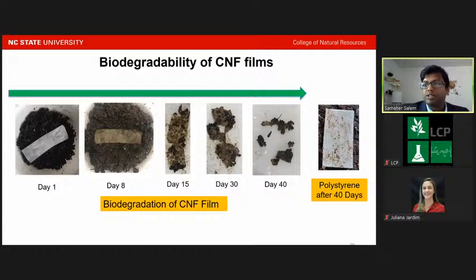And this makes sense because most of the petroleum-based plastics take hundreds of years to degrade owing to their cross-linked covalent bonds, particularly the strong carbon-carbon bonds. In contrast, the oxygenated molecular chain of cellulose can be degraded by bacteria, fungi, and yeast that occur naturally in soil. This combination of excellent biodegradability, outstanding mechanical strength, and high heat and chemical resistance of the nanofibril films suggests they can potentially be used as an alternative for plastics such as polyethylene, polystyrene, and polyethylene terephthalate.